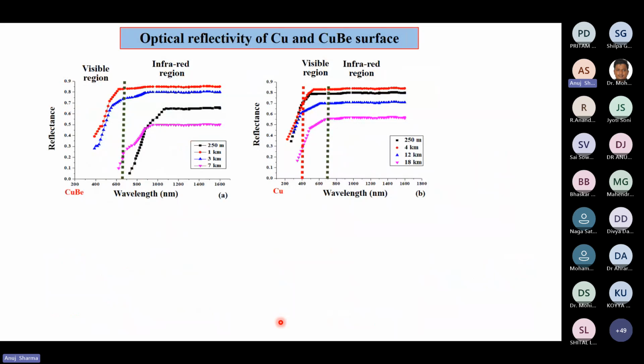Coming to optical reflectivity, since these are nanometric optical surfaces, optical reflectivity was also checked for copper and copper beryllium. Copper surfaces are applicable for the infrared region as well as the visible region. The visible region is 400 to 700 nanometers, and beyond 700 nanometers belongs to the infrared region. Copper beryllium has more dislodgements, voids and projections, so it is mostly applicable in the infrared region. In the visible region, its optical reflectivity falls very rapidly.